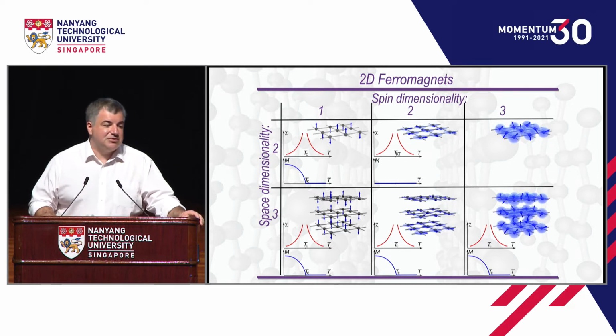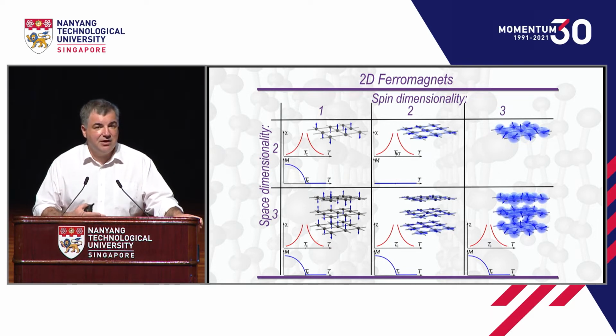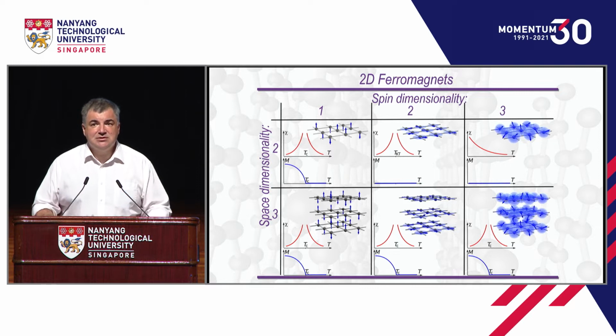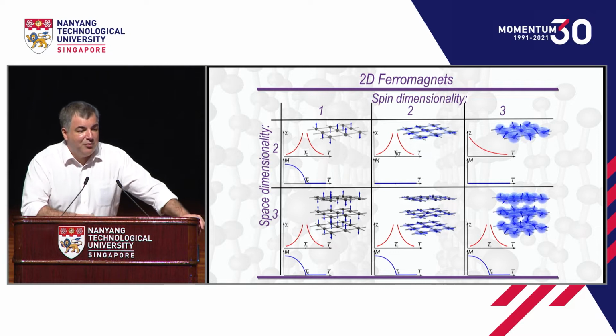So you don't see a jump in the magnetization, in the order parameter, but still you can see some order and some order excitations around the Kosterlitz-Thouless temperature. And in three dimensions, in three-dimensional spin, there are no phase transitions at all. So that just shows you that the moment you get to the dimensionality 2, one-atom thick crystals, their behavior becomes way more complex and way more interesting.